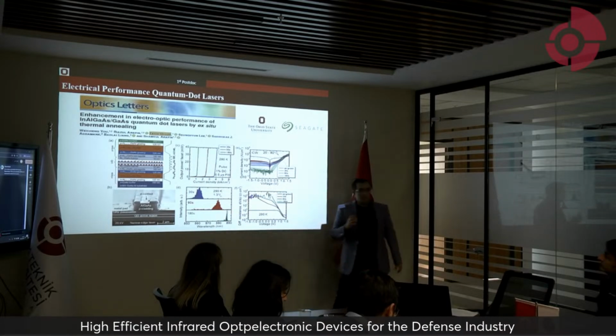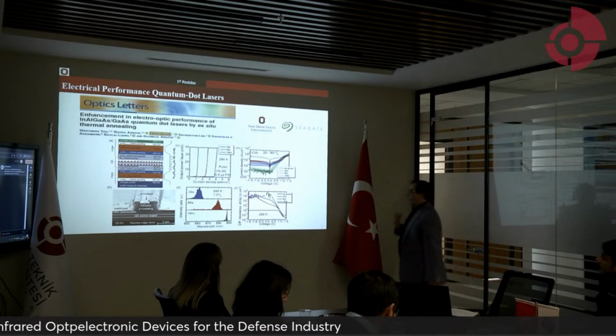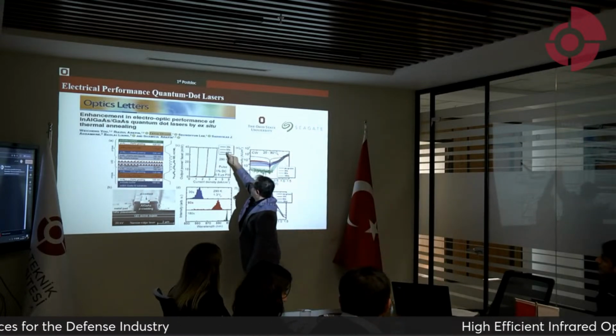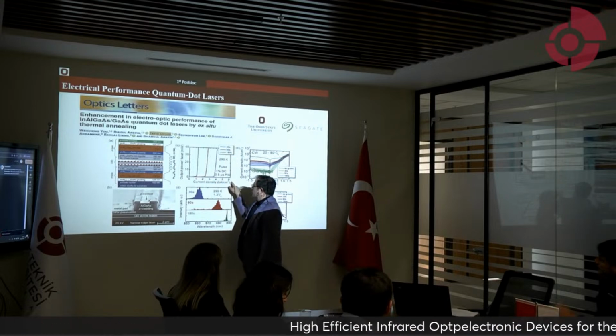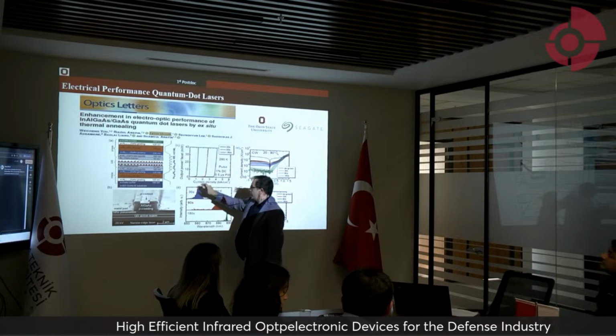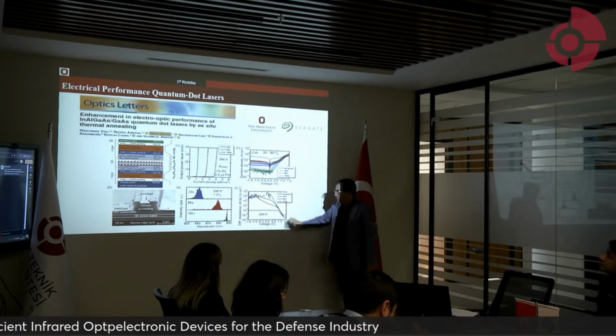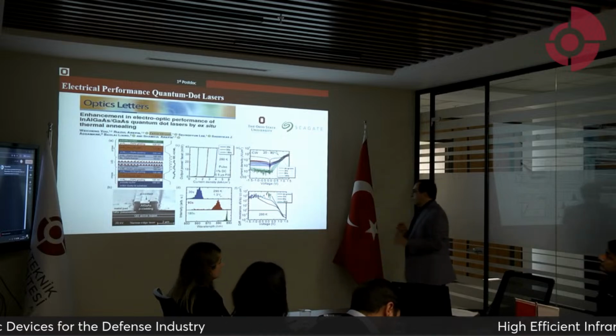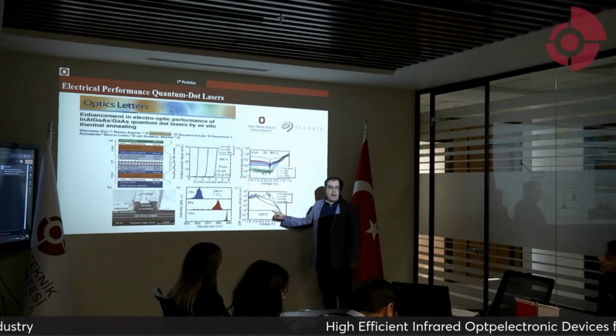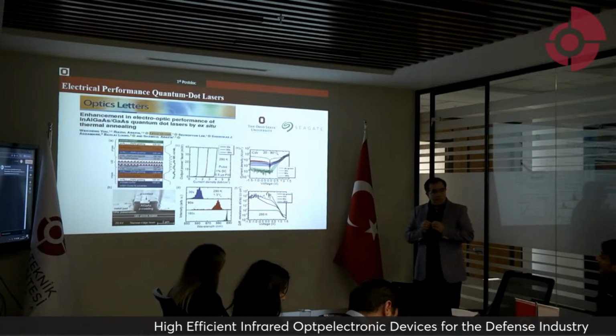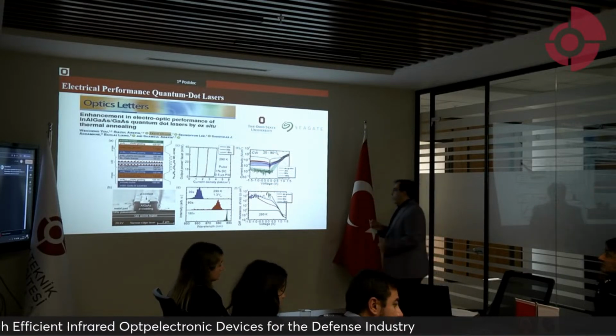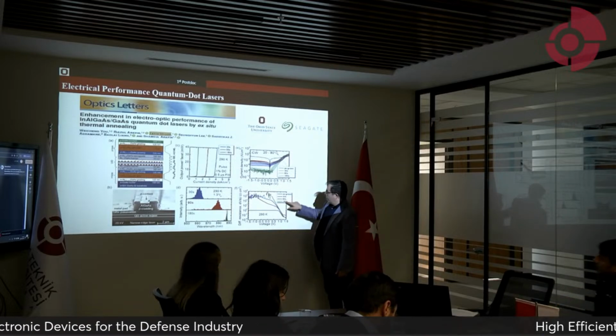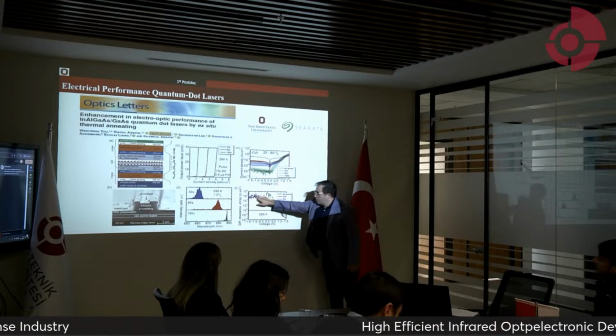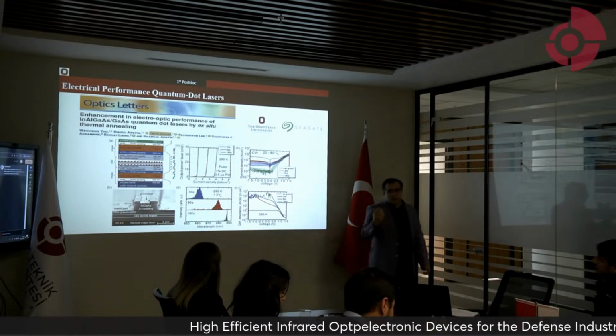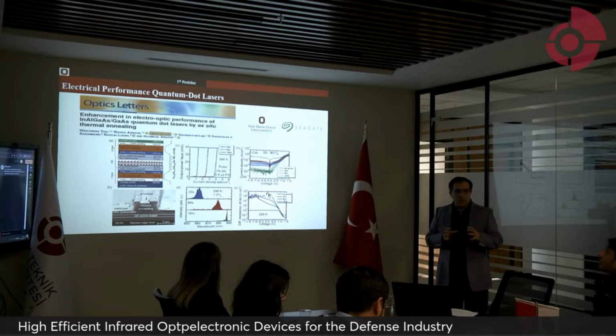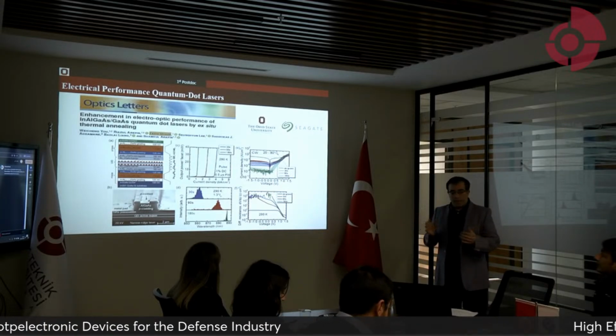The LI graph is very important for the laser area. It shows that with further annealing, the threshold current gets better. And this graph also shows the crystal quality. It shows a kind of resistance of the device. We say shunt resistance. Shunt resistance shows the quality of the crystal, and it means that with longer annealing time, the device shows better crystal quality. Crystal quality is the most critical thing in our field.